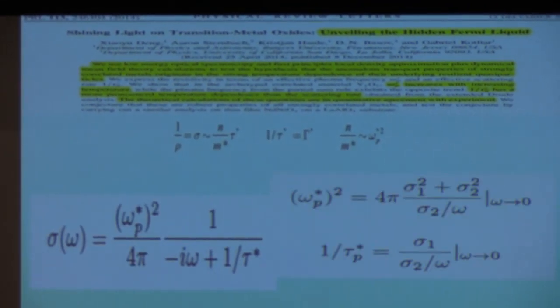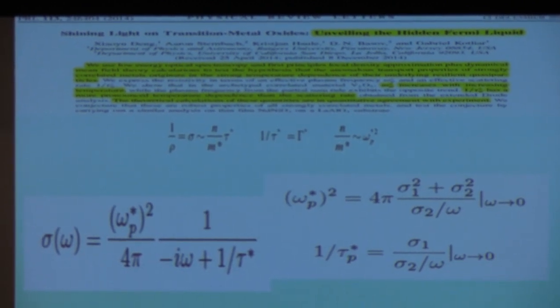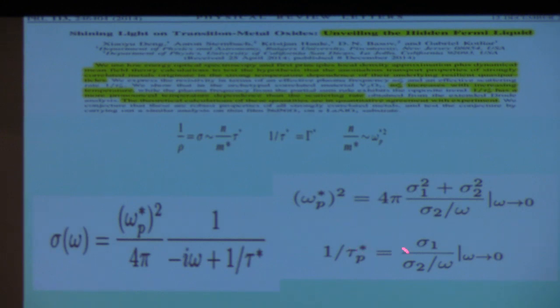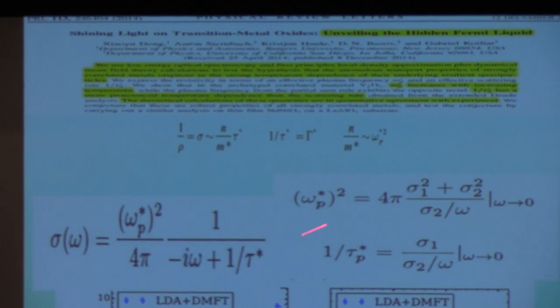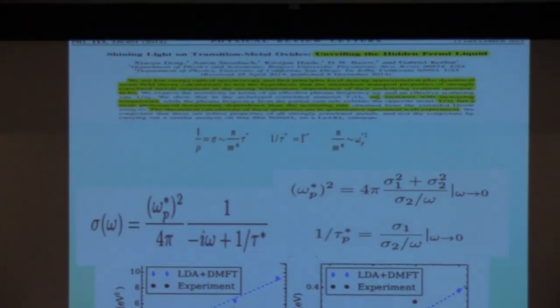And then what we suggested is that we can check if this is true or not by means of optics. Because if you measure the very low frequency optics, you can separately extract the scattering rate, and you can extract this weight, which is what I call 1 over m star. So all you need to do is measure both real and imaginary part of the conductivity. And if you can measure both with ellipsometry and take this limit when the frequency goes to zero, you can measure these two things separately rather than just the product, which is what you get in a static DC measurement. And this is basically the comparison. Now this is our state-of-the-art methods. We really do vanadium oxide. We put the atoms. We run everything. And this is the main confirmation of the prediction, because you see clearly that this mass does depend strongly on temperature.